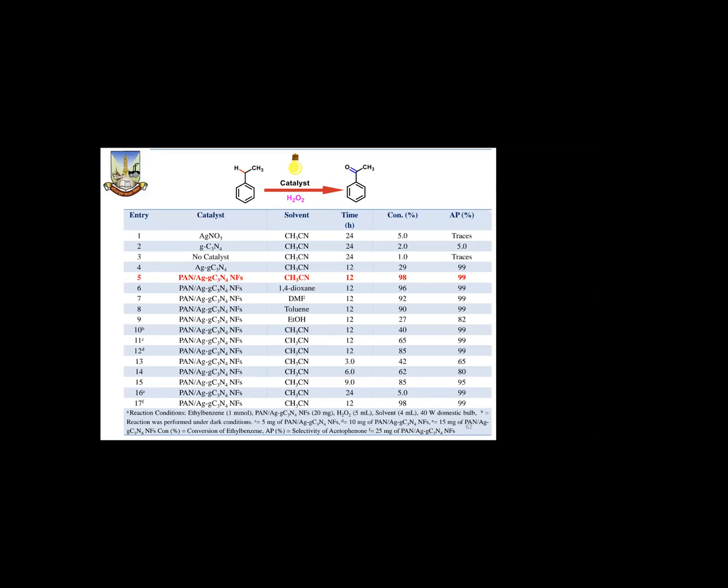In our case, PAN-Ag-C3N4 nanofiber in presence of CH3CN, 12 hours is required and shows 98% conversion. Only a single product is formed, no byproduct.